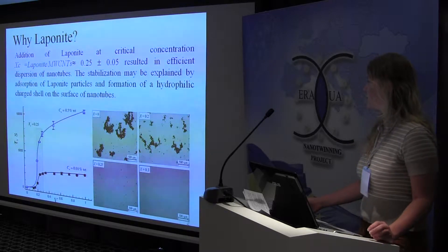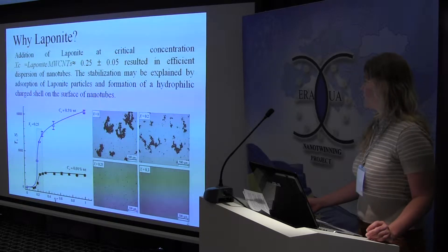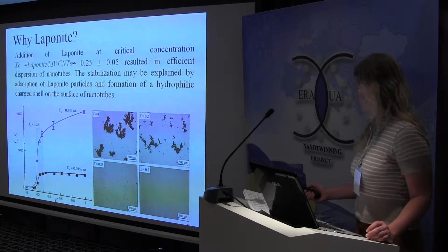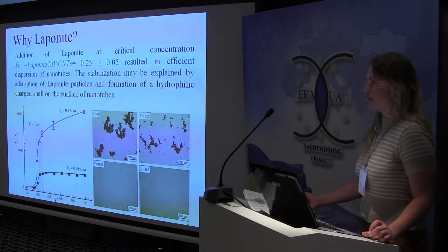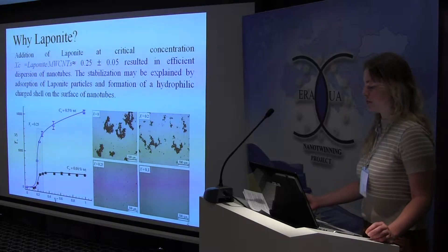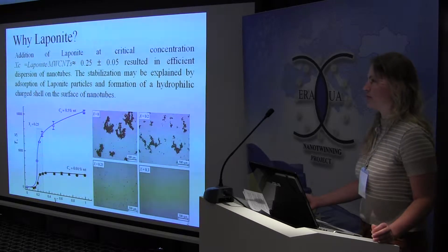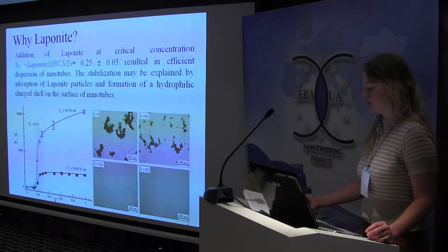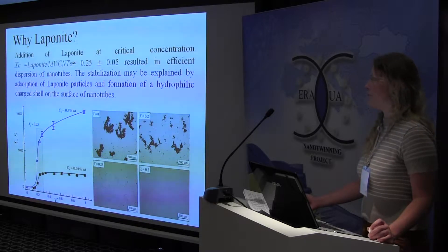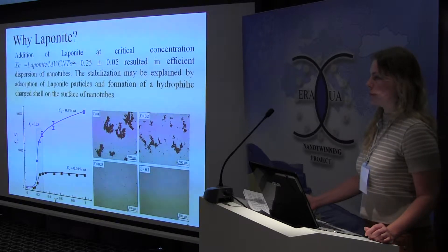If laponite is absent in solution, the suspension contains large aggregates of entangled carbon nanotubes. They cannot be destroyed by ultrasonification due to strong van der Waals attraction between bundled nanotubes and fast re-aggregation of separated, non-stabilized nanotubes. Efficient dispersion of multi-walled carbon nanotubes in the presence of laponite indicates strong interaction between their surfaces.